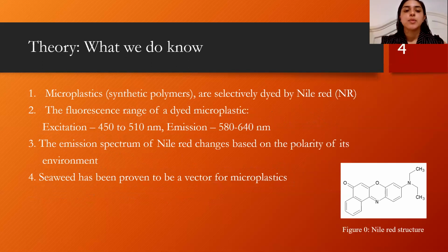So to provide you some sort of insight into the theory that led to my idea of using fluorescence spectroscopy, microplastics are selectively dyed by Nile red. Nile red has an affinity for synthetic polymers and should theoretically not dye any other organic matter that could potentially be suspended in solution. Therefore, fluorescence emission spectra should only be a reflection of the synthetic polymers.